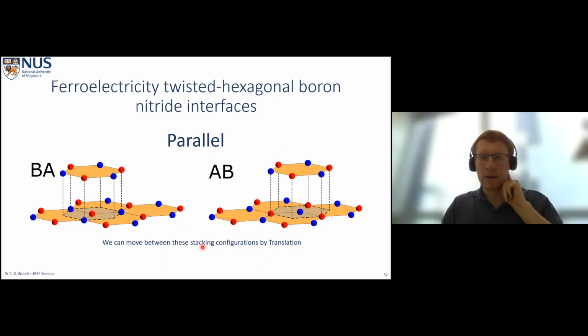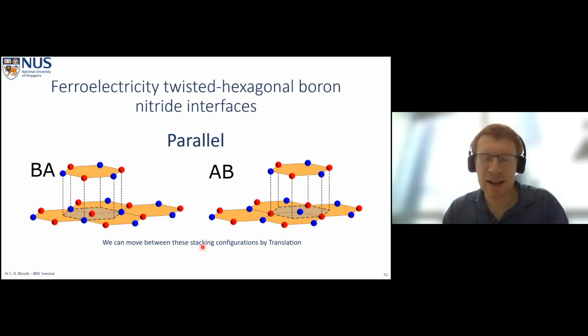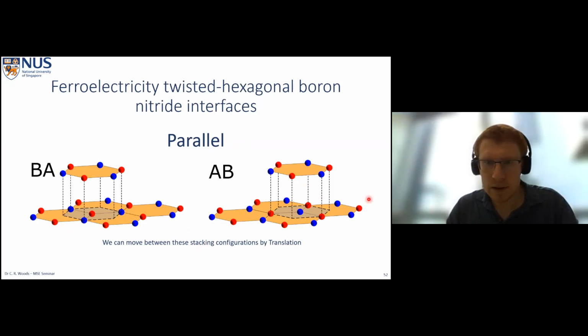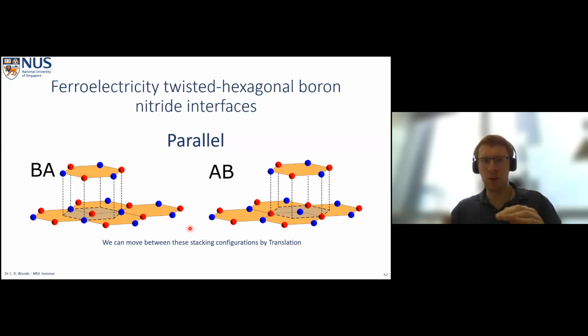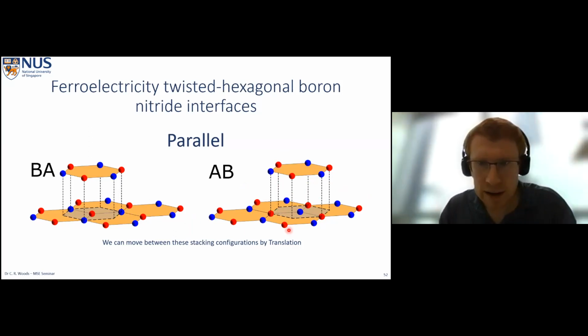And so we can note as well that these two stacking configurations, BA and AB, for the parallel interface have the same binding energy. And the reason for this is that they're actually the same stacking configuration, but just inverted. So if I were to put a mirror in between these two planes, then I would switch from AB to BA, or I could alternately just rotate this round and put this layer on top and this layer on bottom, and I would end up with the BA stacking configuration as well. So I can get between the two of these by just a mirror plane. But another way I can get between the two of these is actually just by a translation. So if I were to translate this unit cell here by one atomic bond length along the basal plane of the bottom interface, I would get to BA stacking. And this is going to become quite important later on.